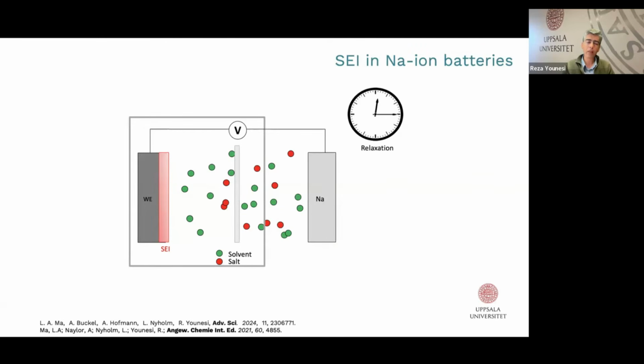This membrane is to make sure there is no crosstalk between the electrodes, because the issue with sodium metal or lithium metal as counter electrode is that the plating and stripping efficiency is not high if we use carbonate-based electrolyte, which is the most common electrolyte. This means that during each cycle, when you plate and strip on the counter electrode, some side reactions form, and those side reactions could move towards the working electrode, influencing the composition, dissolution, and performance of SEI.